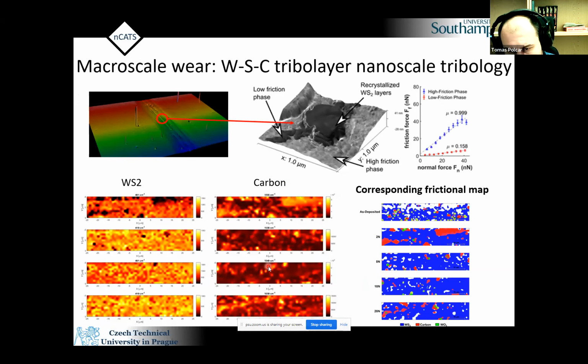So it's very robust. But what I showed so far is that we produce this tribo layer, but we should prove basically that this tribo layer represents a low friction material. And we did it very recently, where we look at this wear track. This is basically when you slide a macroscopic ball over this 1 micron thick coating, you produce some kind of wear path. And if you look inside, and you use atomic force microscopy as your tribological testing, you can really check what is inside, and you find areas like that. And after further analysis, we find out that it's a recrystallized tungsten disulfide layer. You see, this is basically 2D layers, one over the other. And these are very low friction. If it is not there, if you are on some other material, the friction is way, way higher. So we can produce the corresponding frictional map and realize, for example, what coverage of this wear track is by this low friction phase, and then we can do macroscopic models to understand the problem.